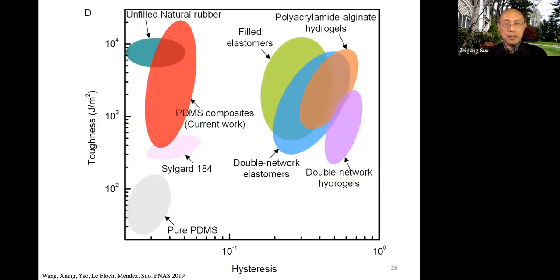All right, now here is our result. Toughness and hysteresis. Remember this old 1966 Nature paper on the correlation between hysteresis and work of fracture, and also toughness: in order to have a tough material, you really need to have a highly hysteretic material. So metal also belongs here. All the rubber you use, synthetic and natural rubber, it's here. Including our polyacrylamide alginate hydrogel and Jianping Gong's double network hydrogel, double network elastomer, and also elastomer, all these materials.